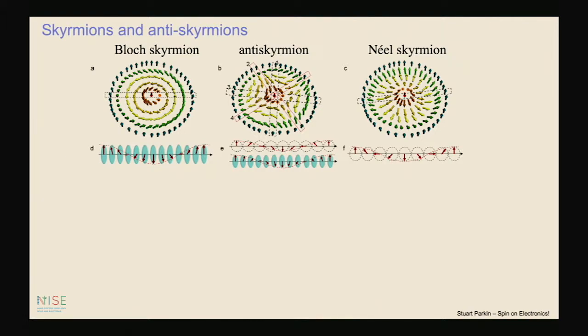And a skyrmion is a very special way of demagnetizing a system in which you have a perpendicularly magnetized system, and you form circular regions in which the middle of those regions are magnetized in the opposite direction, but the wall has a chiral nature, just like the chiral domain walls stabilized by this interface Dzyaloshinskii-Moriya vector. Here it's typically a bulk Dzyaloshinskii-Moriya vector in non-centrosymmetric materials or even chiral materials that stabilizes these skyrmionic objects.